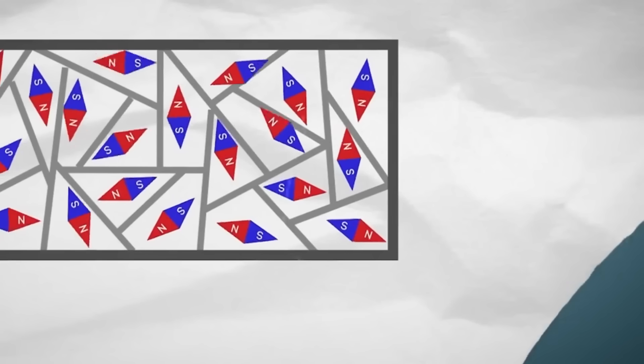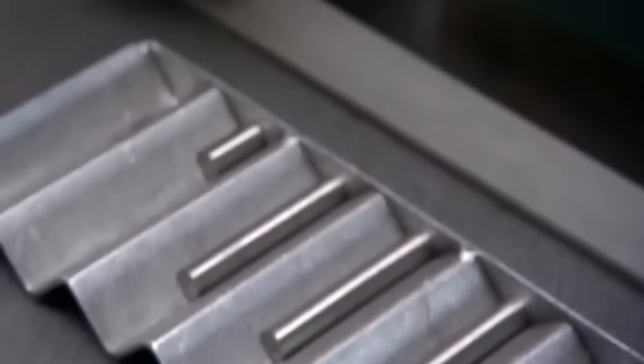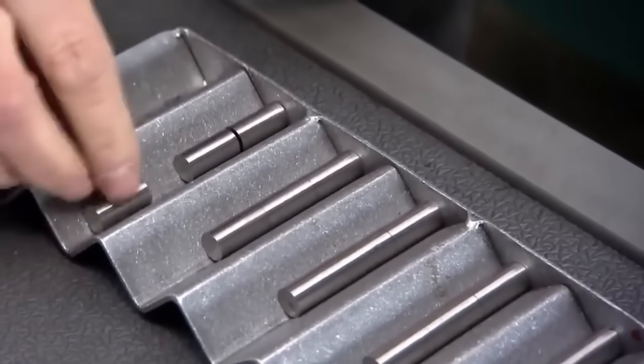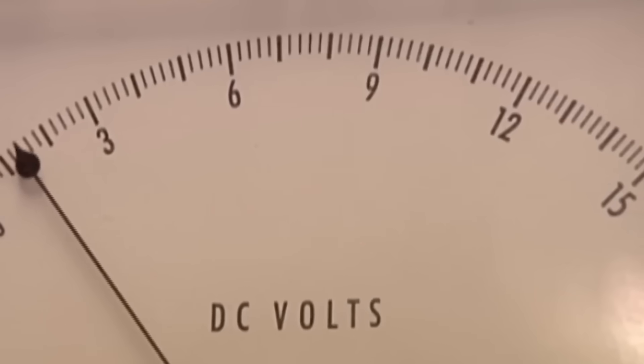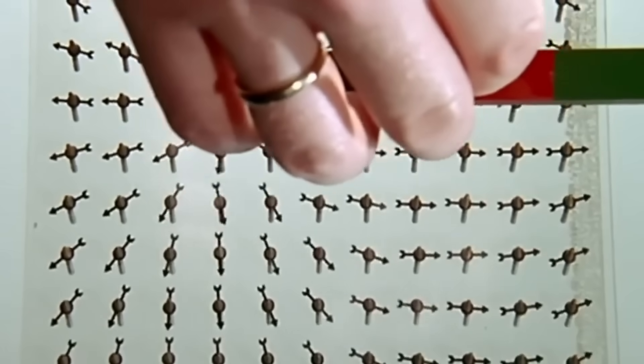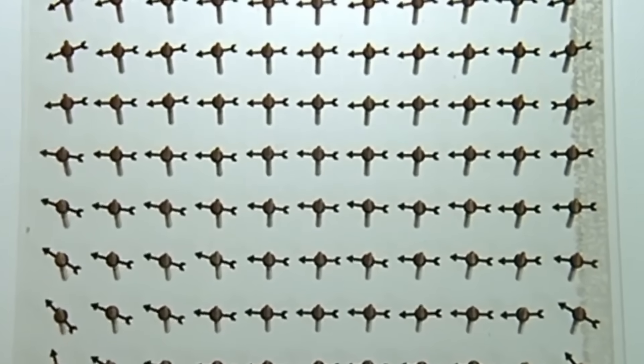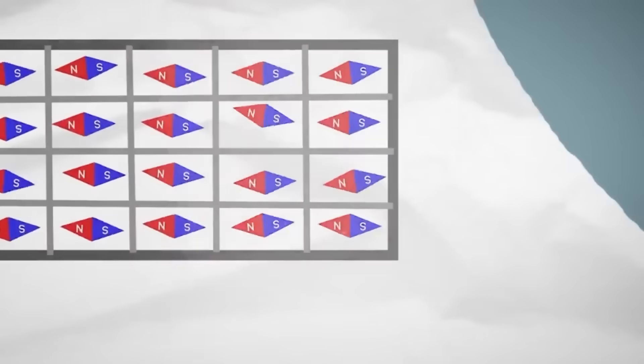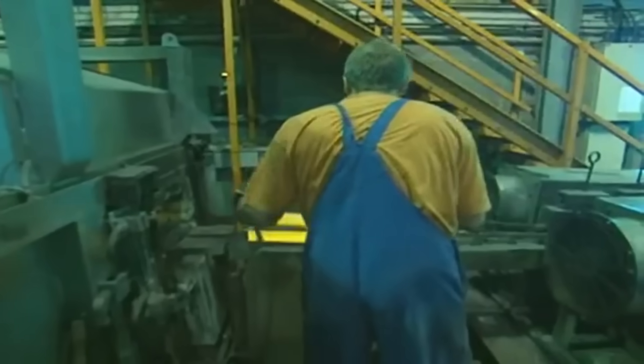Next comes magnetic alignment. A strong, constant magnetic field is applied while the rings are still hot, aligning the material's internal magnetic domains — tiny regions that determine the direction of magnetism. At this stage, the rings become slightly magnetic, and their structure is now aligned for final magnetization. The tube is then unsealed and the rings carefully removed. They go into a machine that applies a magnetic pulse of up to three Teslas, permanently locking the magnetic domains and turning each ring into a high-power neodymium magnet.